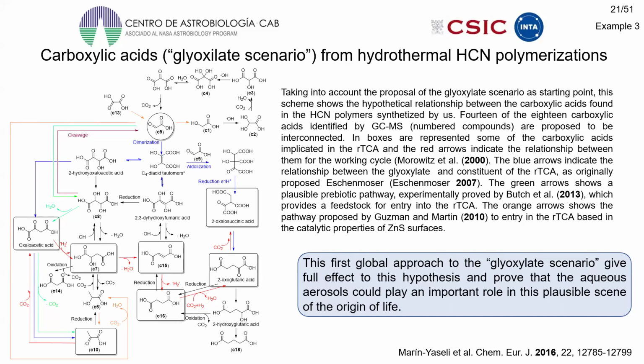In summary of this work, we observed that cyanide reaction led to the generation of several carboxylic acids, among them glyoxylic acid and other carboxylic acids implicated in the reverse tricarboxylic acid cycle, especially when aqueous aerosols are present. This experimental approach gave support to the glyoxylate scenario and also showed how aqueous aerosols significantly improve the generation of polar organics.